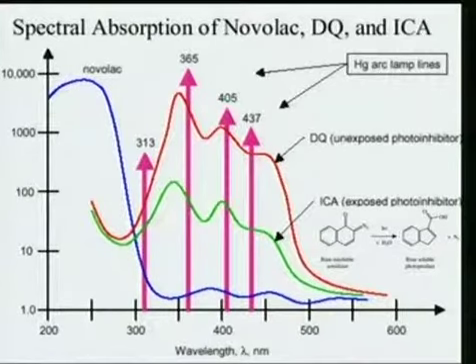The area that didn't get exposed is not sensitive to the base developer. And this system is even better than that, because when it does form this indene carboxylic acid, we have diazo coupling. This thing goes back and attaches to the polymer, and now the polymer is even less soluble in the developer. So we got kind of, I won't say amplification because we use that for the chemically amplified resist, but I would say an enhanced solubility inhibition by using the diazo. So this was a wonderful material.